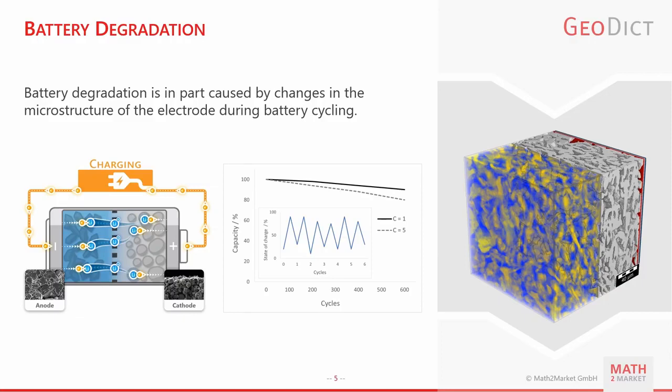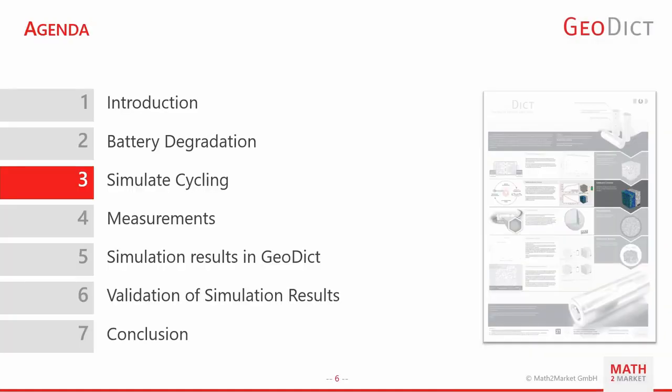These stresses during cycling of the battery lead to degradation of the material due to cracks, delamination, and deformation of the inactive layers and the casing. The altered microstructure is said to age, and it suffers from capacity loss and damaging effects like lithium plating. If a battery is cycled, of course, these degradations sum up during each cycle.